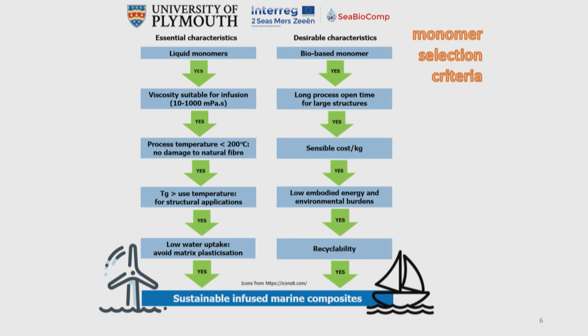It needs to be liquid at the temperatures that we want it to flow. The viscosity has to be suitable for infusion. If it's too low, you tend to trap air. If it's too high, it doesn't get to the end of the product. The process temperature, because we want to use natural fibres, needs to be below 200 degrees centigrade. The use temperature ideally will be below glass transition temperature for ease of design.